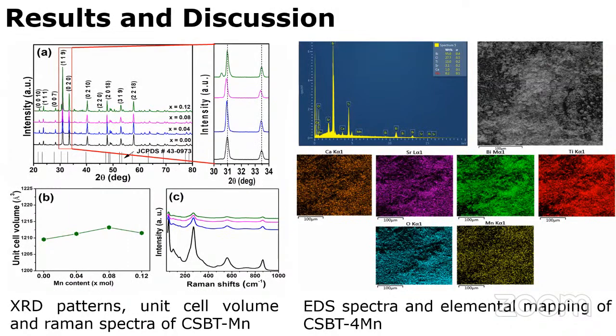On the left side, you can see the XRD patterns, unit cell volume and Raman spectra of CSBT Mn. In the XRD pattern, we can see a peak near 33 degrees. The maximum peak can be observed at (119), which meets the criteria for BLSF. The unit cell volume has also been calculated with the help of XRD, and Raman spectra was also recorded. On the right side, you can see the EDS spectra. With the EDS spectra, we can see a uniform distribution of the additive, MnO2, throughout the composition. And since bismuth is a volatile element, we can see that the bismuth has also evaporated uniformly throughout the whole surface.